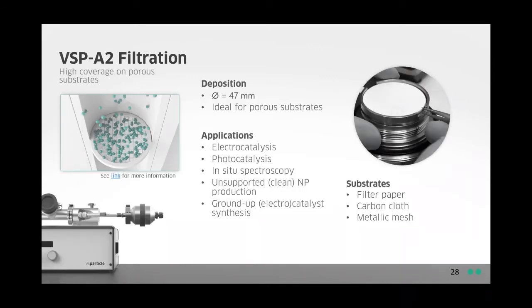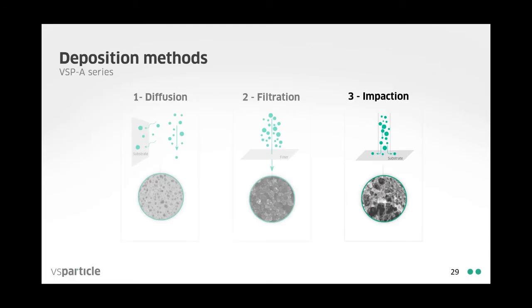The substrates we're compatible with can have a maximum diameter of 47 millimeters, and what's really important, since it's filtration, is that the substrate needs to be porous. Applications where we see this being relevant are electrocatalysis, photocatalysis, in situ spectroscopy, the preparation of unsupported clean nanoparticles, and ground-up electrocatalyst synthesis. Common substrates that can be used are filter paper if you want clean nanoparticles, carbon cloth, and metallic meshes.